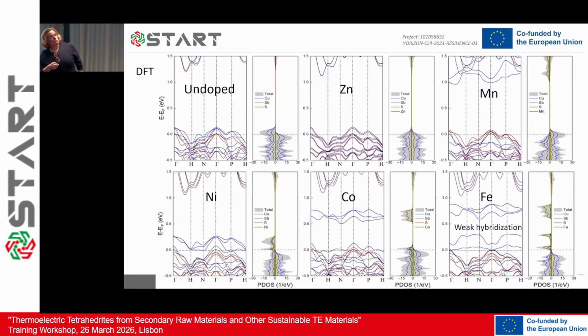What you see is that when you replace copper with zinc, there's not so much difference in the band structure of tetrahedrite. The same with manganese. And then you start to see that you generate some defect states that go into the band gap. But all in all they are quite okay because you still have the Fermi level within the valence band.